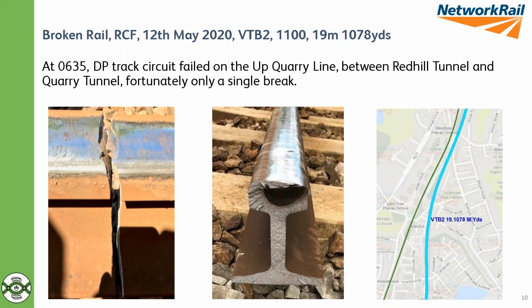So some fortunate ones there where we didn't end up with a derailment, but in other situations it potentially could have been a lot more serious incident. So it's one of the challenges. Although we've reduced broken rail numbers, we've not eliminated them, and the risk still is out there. And that's something certainly from my point of view that is concerning, that this sort of defect, particularly transverse defects in the head, should be something we are able to prevent through inspection. And so a little bit more, but that's likely to be still subject to the inquiry.